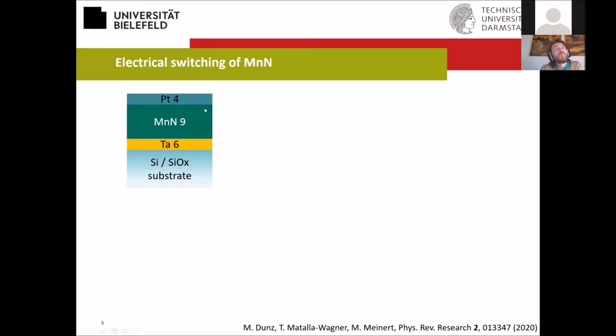We took somewhat thinner layers of the manganese nitride. So here we went for 9 nanometers to exploit the weak anisotropy of the material. At 32 nanometers, we get maximum exchange bias, so we were expecting to get a little bit easier switching at thinner films. This is why we went for 9 nanometers, and for comparison, we also did 6 nanometers. And then we grow a platinum layer on top of this.